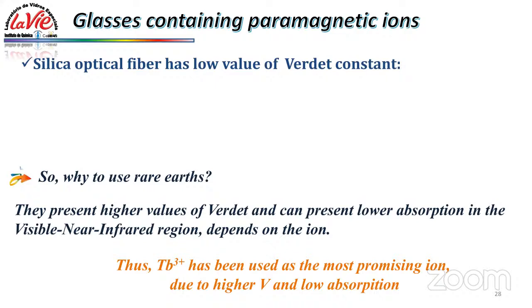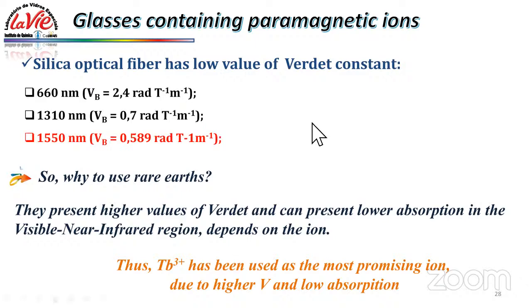When you talk about paramagnetic ions, compared to what we can find in the literature and on the market, we have the silica optical fibers. These are the Verdet constants of the silica. For example, at 660 nanometers, the Verdet constant is 2.4 rad per Tesla per meter. At 1310 nanometers it is 0.7 rad per Tesla per meter. And in the telecom range, it is something around 0.589 rad per Tesla per meter.